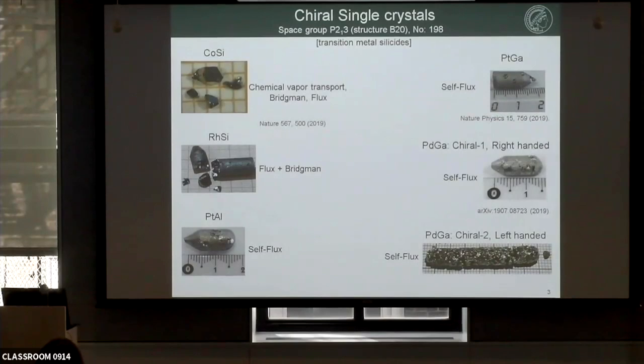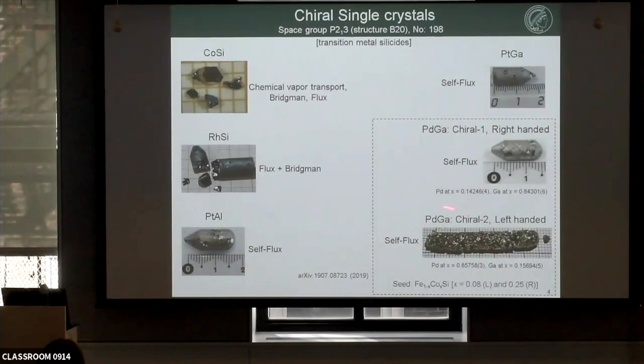Next, I want to talk about two opposite chiral crystals for ARPES. I grew these two different crystals using a seed — cobalt-doped iron silicon. It's already shown in literature that up to 10% cobalt doping, this is a left-handed chiral crystal, whereas if you increase cobalt doping to say 25%, it forms a right-handed chiral crystal. These single crystals are used as seeds for forced crystal growth of opposite chiral crystals. Using X-ray absorption spectroscopy to determine the structural chirality, we can see that the Wyckoff positions of Pd and Ga are simply opposite, confirming these are two opposite chiral crystals.